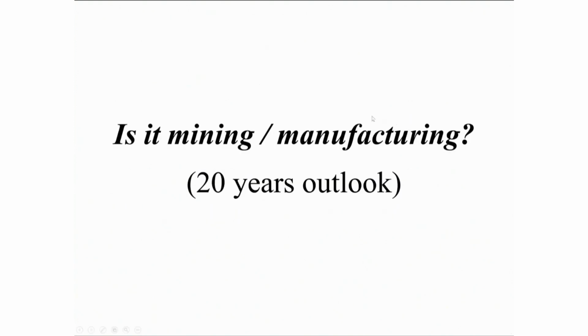Is mining or manufacturing the problem? It indeed is a huge problem, because there is still a factor of 10 to 20 to go if we want to completely replace all the internal combustion engines in the world, not just in developed economies. And so if we want to hit it by 2040, 2050, then we have to have a year over year 25% increase in the already significant lithium mining, cobalt mining, cell manufacturing, pack manufacturing. And that is, like I said before, not something to be considered lightly. It's a tremendous civilization-scale endeavor.